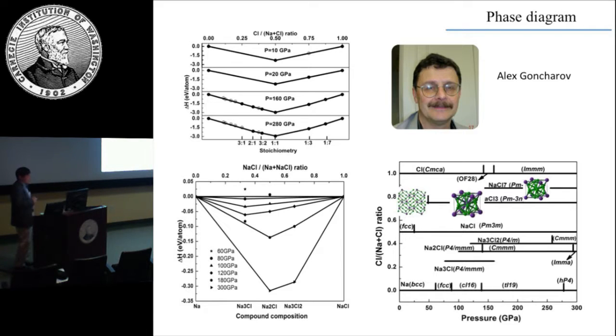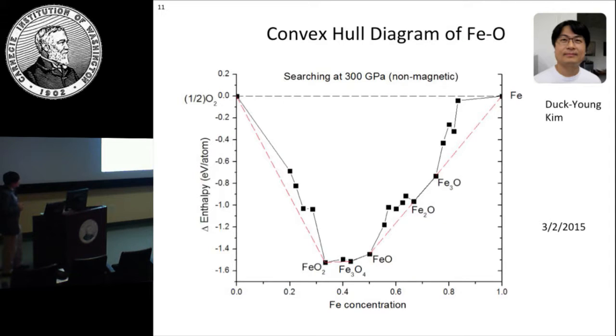So this itself is kind of shocking chemistry, because that means that you don't look at the charge anymore. You just look at whatever the lowest energy phase will be stable. Okay. Now, so then we look at the FeO. Initially I was interested more in this side, like between iron and FeO, because that's the iron boosted side. I said that the lower mantle is mostly iron boosted buffer. But instead, Dr. Duck-Young Kim found that there's a phase that's sticking out, FeO2. It's way below everything else.